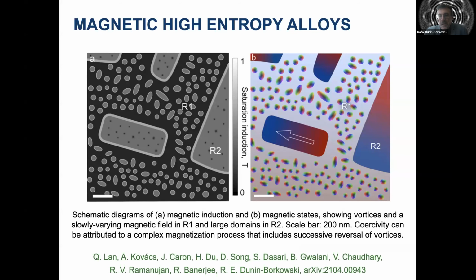And on the right-hand side, what off-axis electron holography tells us is that these different regions have very different magnetic properties. Some have large magnetic domains and some have vortex-like magnetic states. And the reason the coercivity is so difficult to understand results from the complexity of the magnetization reversal process through this physical and magnetic microstructure, which involves successive reversals of the different magnetic vortices in the different precipitates.